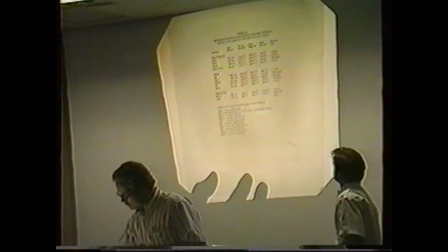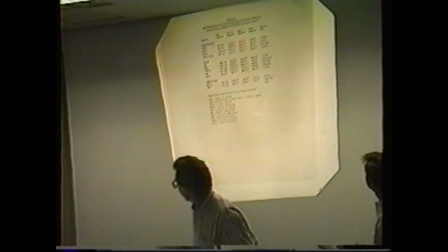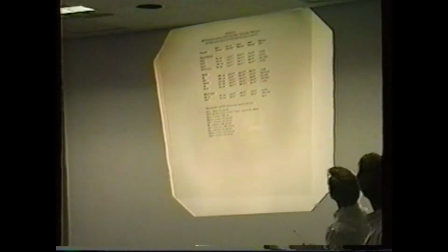Yeah, he has an overhead that answers that question. What's the detection level converted to, like milligrams or moles, for a scanning object? It's a little bit hard to read, but the middle column says grams analyzed. And the only important point to point out is those are between 10 to the minus 12 and 10 to the minus 17 grams analyzed total.